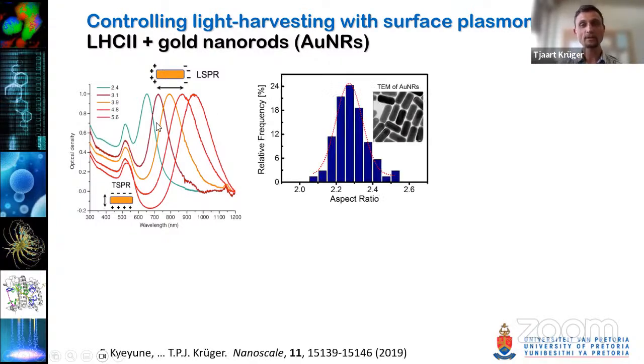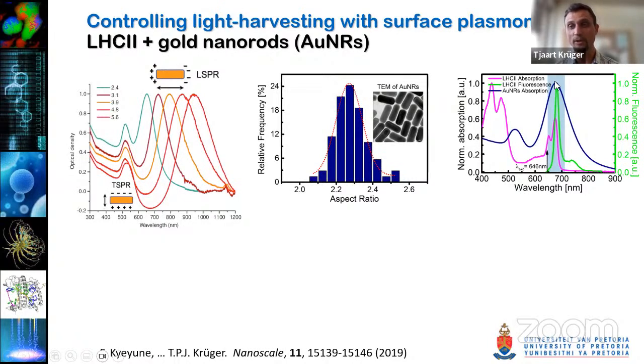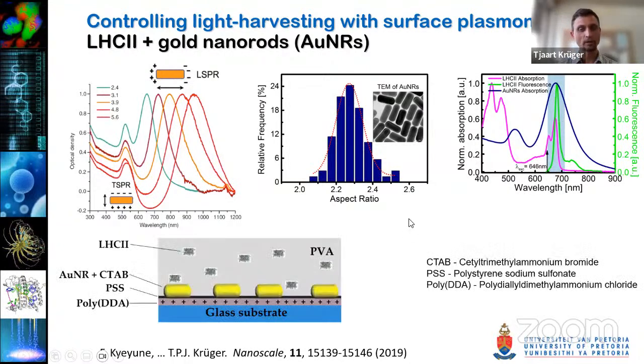Okay, so we synthesized gold nanorods of a certain aspect ratio such that the absorption spectrum was in resonance with the absorption and fluorescence of LHC2, which you can see there. And then we used layer by layer assisted methods in order to first put the nanorods on the glass substrate and then spin coating LHC2 in between them. And then we would do single molecule spectroscopy on LHC2.